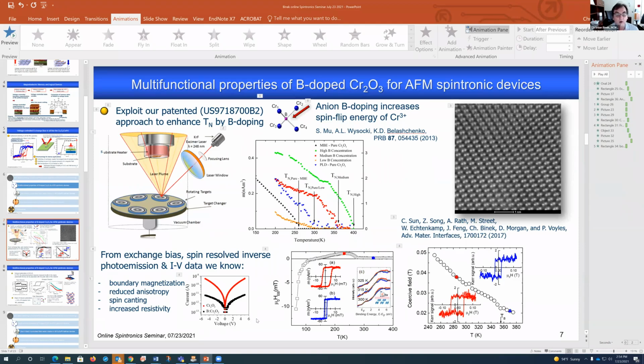These are actual data from our films. This doesn't tell you much unless I give you the numbers of the electrode sizes, which I don't have handy. But in this case, we had a prefabricated Hall bar, and just used the Hall bar cross as one electrode, and the entire bottom as another electrode, and then applied this type of voltage across the structure and measured these currents. So yes, there's leakage.